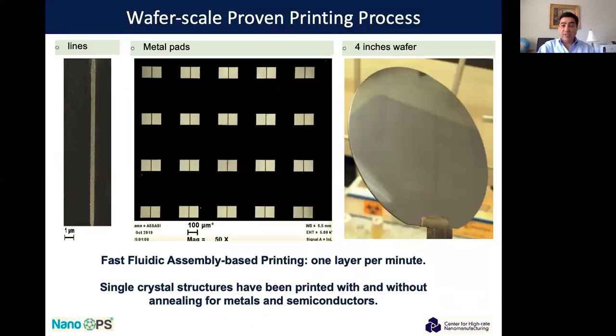This is an example. These are about 37 transistors, basically the source and drain, done on a 4-inch wafer. And each layer takes 1 minute. So in 1 minute you can get about 37, and you can go up to 100,000 or more, or a million per wafer, for example, and it still takes 1 minute per layer. And as I said, we had single crystal structures built from metal and from semiconductors.